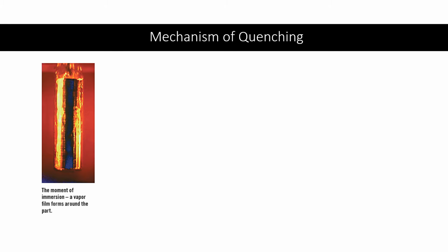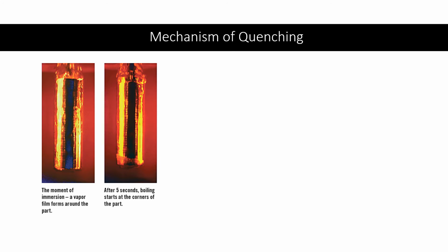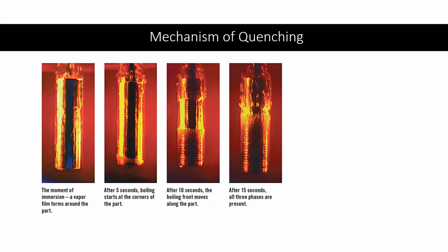I will now show you the still images sequencing the mechanism of quenching. The moment the heated object is immersed in the liquid, a vapor film can be seen forming around the object. After 5 seconds, boiling starts at the corner of the object. And then after 10 seconds, the boiling front moves along the object. After 15 seconds, all three phases can be seen.